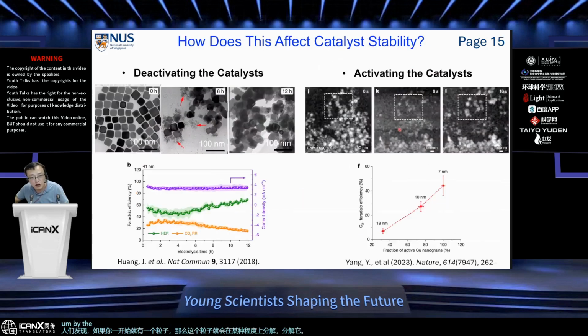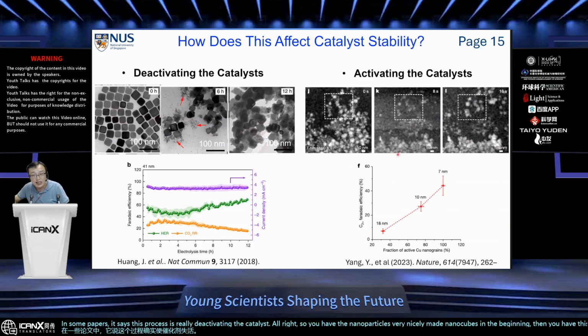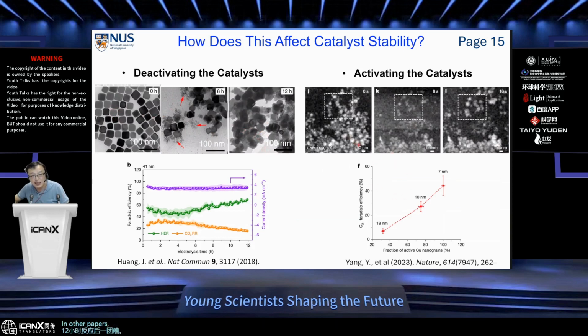But for the cause of this behavior and the result of this behavior, you'll find that there is no coherent view in the literature. In some papers, it says this process is really deactivating the catalyst. All right, so you have the nanoparticles, very nicely made nanocubes in the beginning, then you have this big mass after 12 hours reaction. In other papers, they claim that this sort of reconstruction activates the catalyst. Okay, so these two views obviously cannot be correct at the same time.